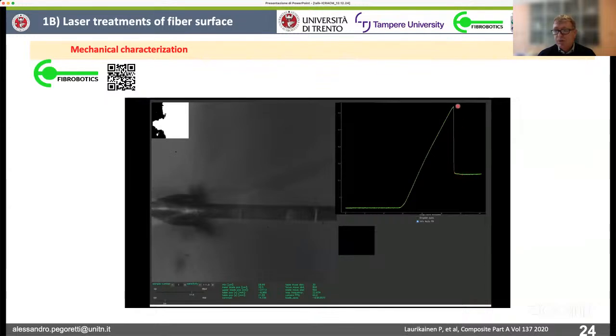So basically we separate the fiber from the matrix. Of course, the load does not drop to zero because we have some friction between the fiber and the matrix. So this plateau represents the frictional forces between the fiber and the matrix, which are also interesting to be measured. The maximum force is here, and from this maximum force, we can measure the interfacial shear strength according to a model.